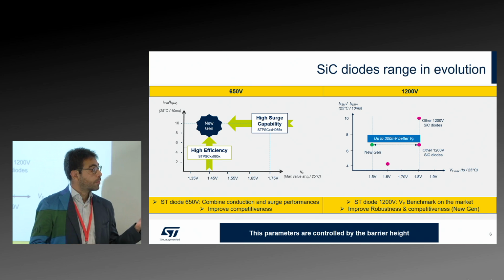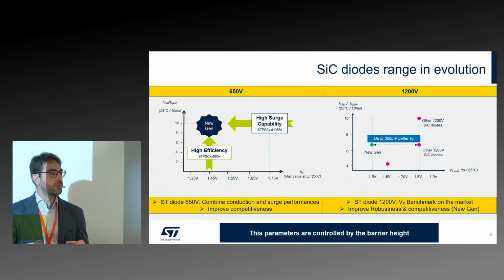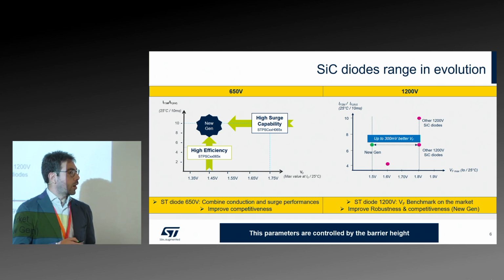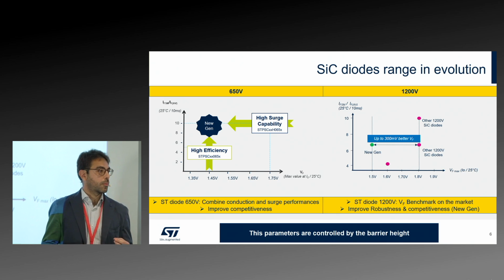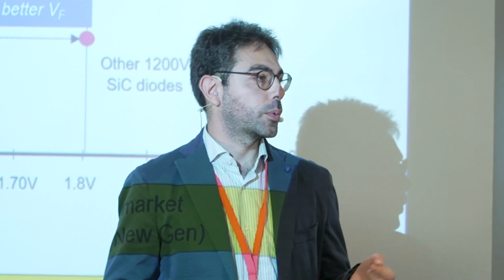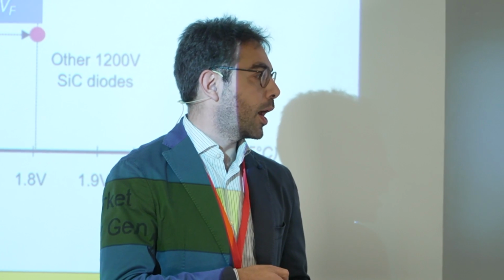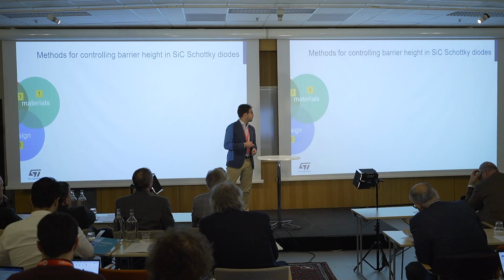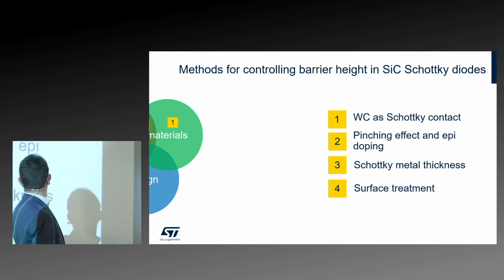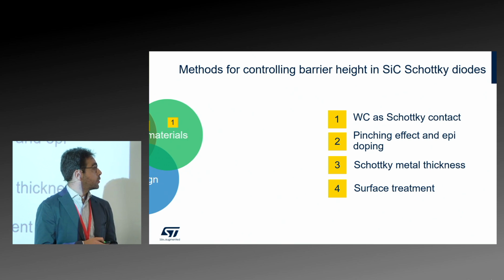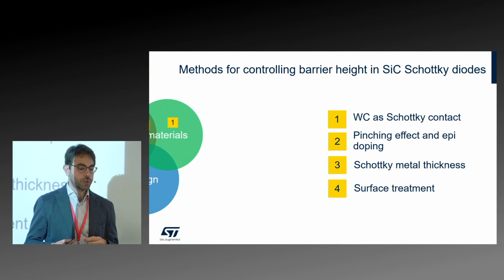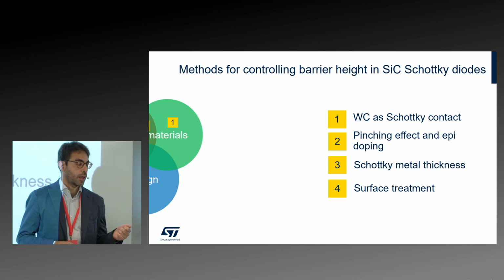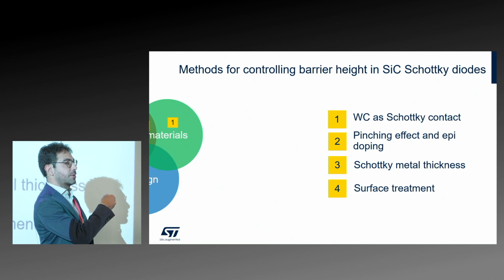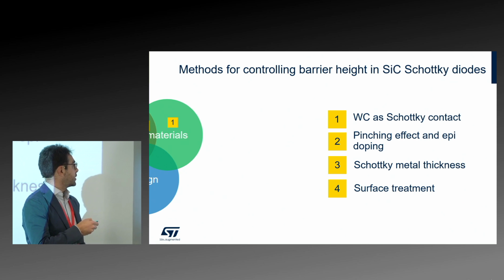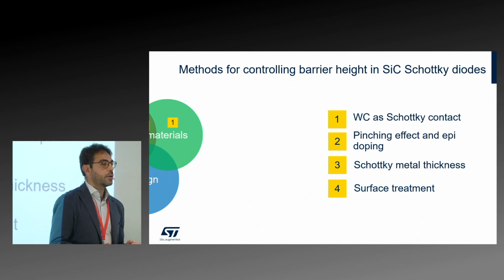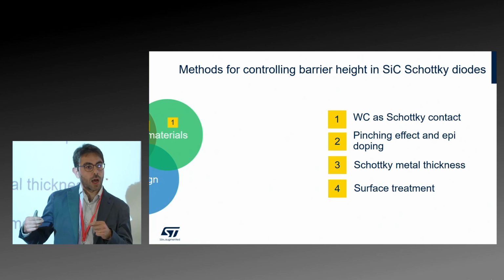But as you know, to obtain all these results, we have to play with different technology changes. One of them is the barrier height, because in silicon carbide diodes, JBS ones that we are talking about, the Schottky barrier height plays a key role. What I would like to give you is an overview of which approach we used. We can play by changing the materials, the design, or the process. Basically, if we change one of these parameters, we can modulate our Schottky barrier height.